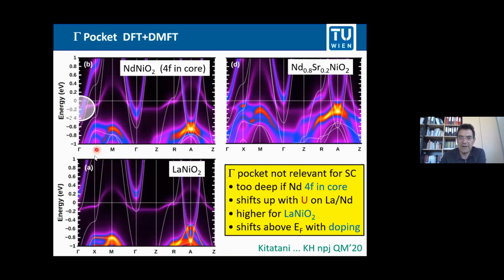That electronic structure I already have shown you before for the lanthanum compound. For the neodymium compound, you see here the gamma pocket, and that's the first one I'd like to talk about. For lanthanum, we find it to be above the Fermi energy because we take into account also the CRPA Coulomb interaction calculated on the lanthanum or neodymium sites, and that pushes the gamma pocket up. So in the lanthanum compound, it is not there. In the neodymium compound, it is there.